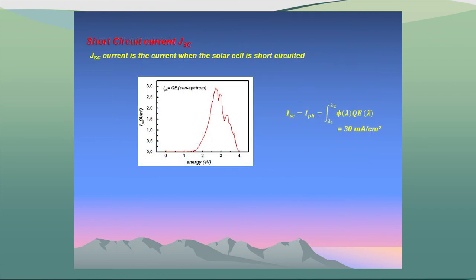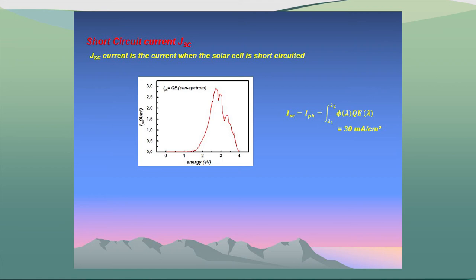For the pin junction photovoltaic device, also very important is the short circuit current. This short circuit current is obtained by integration — when I take this and integrate all the area under my curve, I find around 30 mA/cm². This value is slightly higher than what was shown this morning. But using another way to calculate this photo current, my value will be in nice agreement with it.